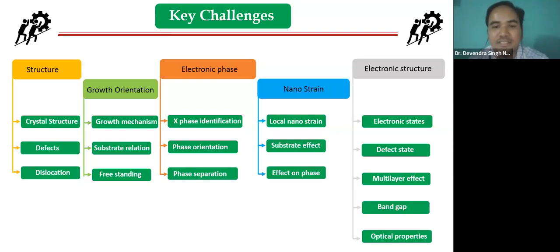So therefore, understanding this nanoscale or atomic scale strain is very crucial, and transmission electron microscopy can give you this understanding. So now we can see how much strain is coming between 2-3 atoms in the surroundings, how much strain is taking place if we are on the edge or on the center of this material. So that could be understood. And for this material, understanding strain is very important to see how this strain is changing the phases of the material. And it's also very important to see how the substrate is affecting this strain, and how this strain effect is driving the new phase formation.